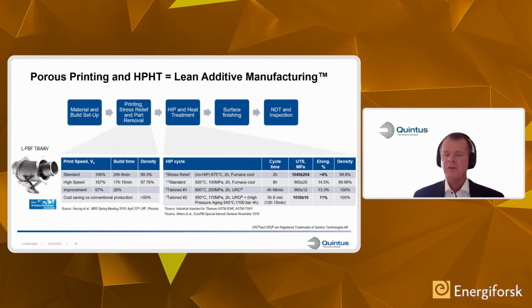And by elaborating with different types of HIP cycles together with that, we can actually achieve mechanical properties that are well within limits. So the standard HIP cycle for titanium is 920 at 100 megapascal, 2 hours, furnace cool. But we've proven that you can both go down in temperature and up in pressure and achieve mechanical properties that are sufficient. So there are possibilities to elaborate. However, standard dictates that it should be 920, 100 megapascal. There are possibilities to increase speed and increase productivity.